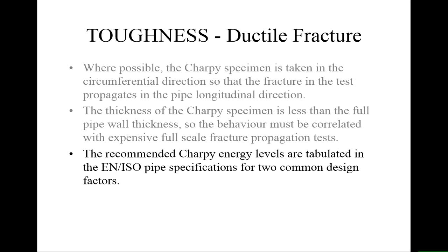And after doing that, recommended Charpy levels have been tabulated in the pipe standards. So we've got a strength criteria, and we've also got a toughness criteria in the standards that the material has to meet. Now, of course, these are all things that you can do with any composition of steel you like. So the standard specification does not fix the composition of the steel, it just fixes the properties that you need. So as long as you can achieve those properties, including the mechanical strength and the impact toughness, then you could use anything to make the steel for a pipeline.